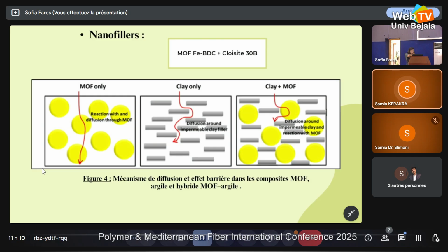So diffusion must travel around the clay layers and interact with the MOF structure, creating a tortuous and complex pathway that strongly reduces permeability and migration. This synergistic mechanism explains the enhanced barrier properties observed in our system, as we will see in our results.